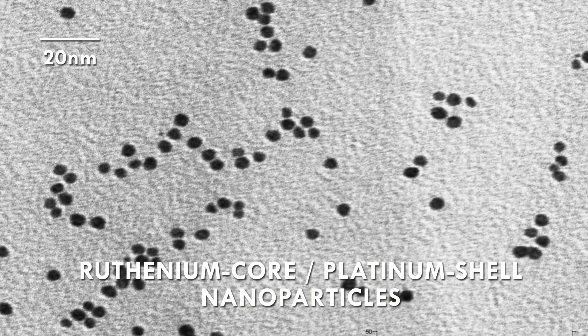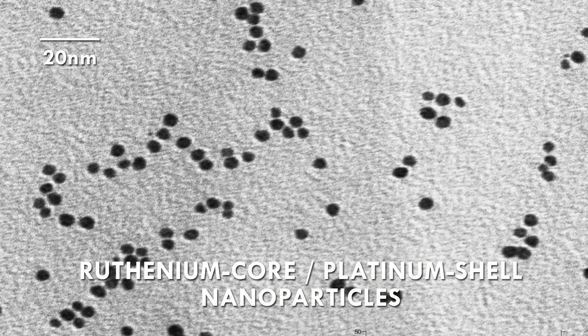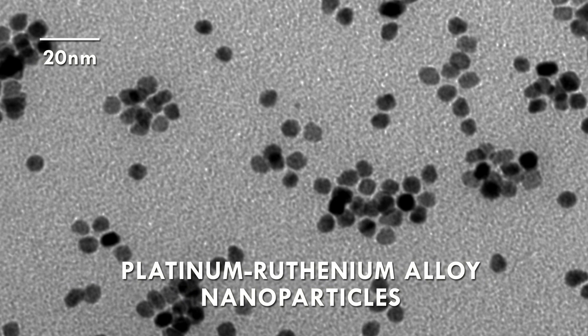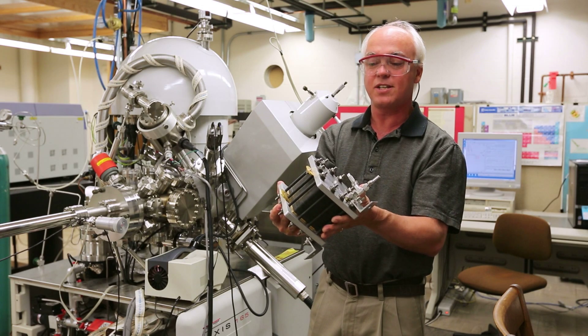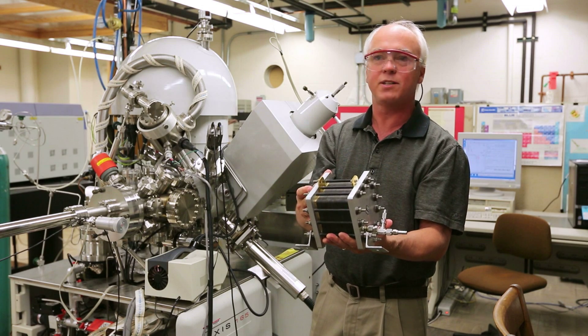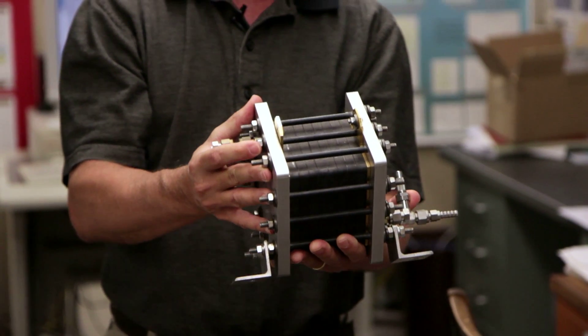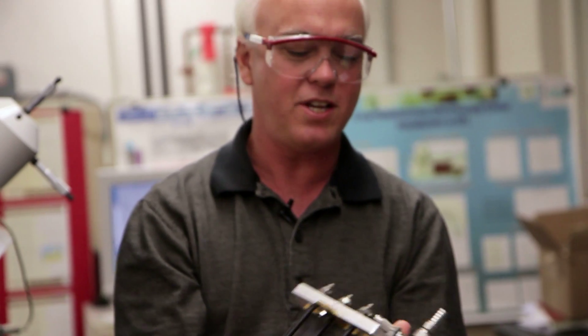So we're trying to get away from platinum, but in the meantime we've been able to make new particles that go into these cells — very small, a few thousand atom particles that use a lot less platinum in the actual catalyst. And now a cell this size today generates about a kilowatt — can run, in fact, a refrigerator — and has about a tenth of the amount of platinum. So they're cheaper, they generate a whole lot more energy, and in fact they're now commercially viable and being sold.